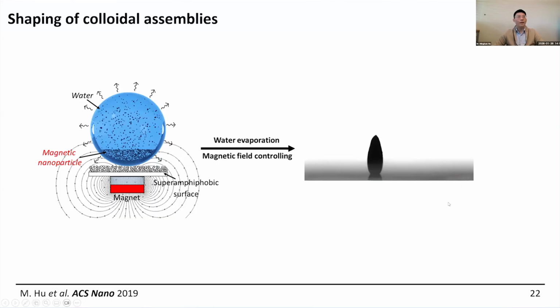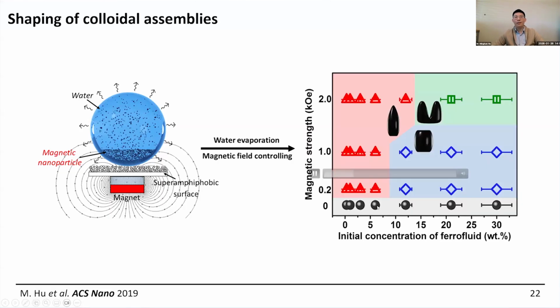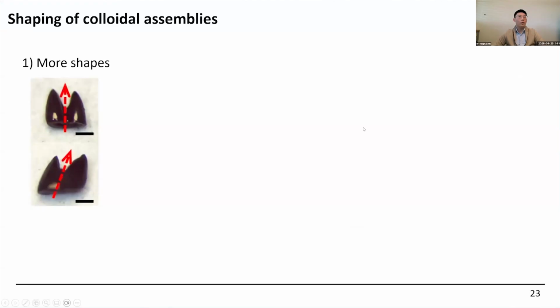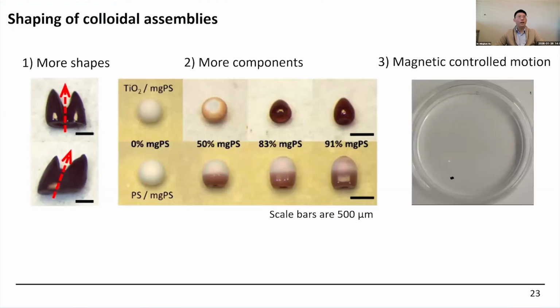And with that, we also play around with the magnetic particle concentrations as well as the magnetic field strengths. Then we can control the shapes from this cone-like shape to the barrel-like, also the double tower-like shape. And this is very nice. And furthermore, we can also tune the magnetic field orientation to tune also the final shape orientation. And we can also add more components inside.